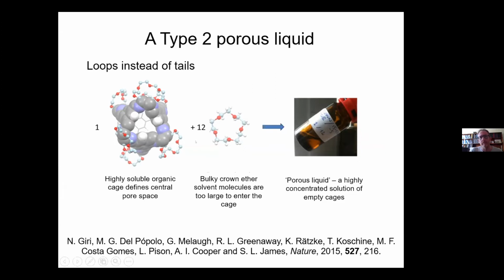We made this. We dissolve it in a solvent which is too big to fit inside the pore, okay? So this is an unusual solvent. This is actually a crown ether, but it's perfect for what we want to do here. So you take this host, this cage, you dissolve it in the crown ether, you get a clear solution which now has permanent empty spaces in it. This is a porous liquid.